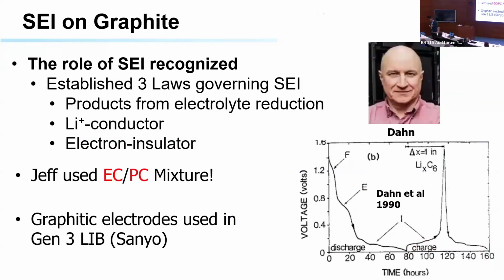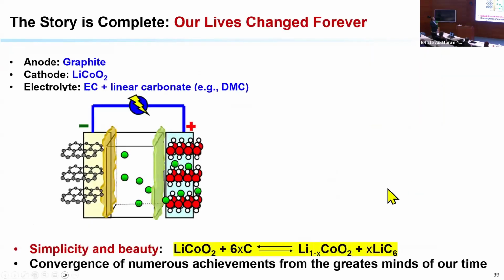And the summary is right here. This is a Canadian gentleman. Basically, he summarized it. What he found out is that this combination of ethylene carbonate and propylene carbonate was nearly ideal for the graphite and enabled the graphite to work. And this was the first time that it was shown that an electrolyte that is compatible with the graphite, forming this compound, is realized in real life. And basically this completed the story. Graphite as anode, lithium cobalt oxide as cathode, and EC plus a linear carbonate as electrolyte.